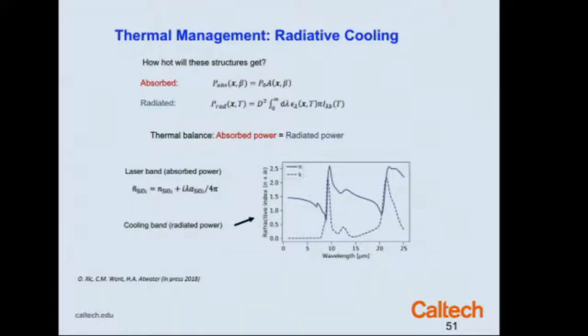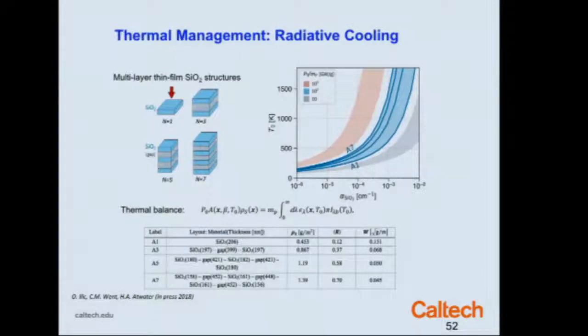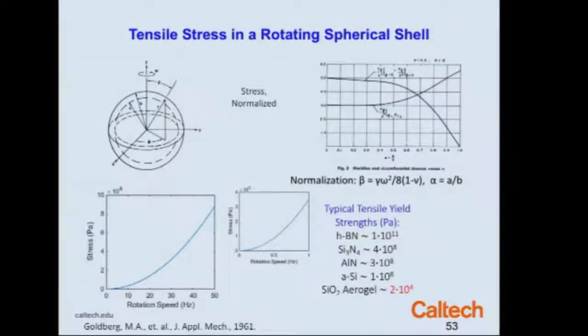Many of you may know, if you've ever shined a long wavelength laser, silicon dioxide, which is transparent in the visible, is opaque at 10 microns. So this allows the appropriate balance. And even with emissivities in the range of 10 to the minus 3 or 10 to the minus 4, we could keep the temperature of the sail to maybe 500 to 700 Kelvin. So a couple hundred degrees C, which is probably acceptable within the range of things we're interested in.